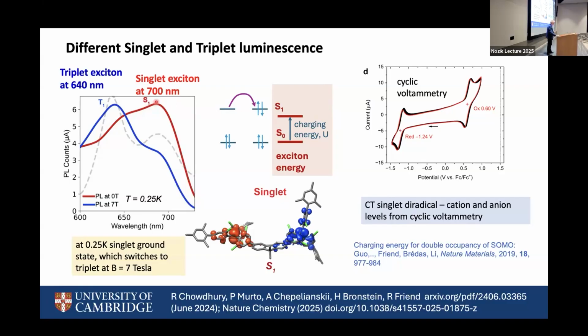And the colors change. We go from 700 nanometers to 640 just by applying a magnetic field. So the magnetic field energy is about 1 Kelvin. The color shift is about 250 millielectron volts, that's 3000 Kelvin. But the gating of what excited state we can make is just by the initial spin configuration, just flipping it, determines whether or not we can get this charge transfer process, which is what we're getting with our photoconductor. And if we do, we get the redshift of emission.